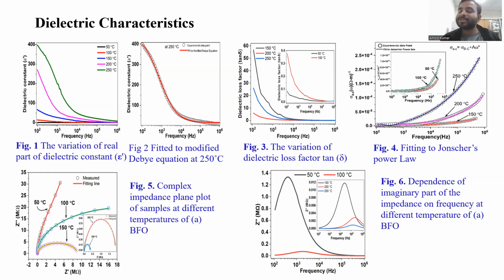In this fitting, we get S, and we draw the graph between S and temperature, and we know which type of model it is. If S decreases with temperature, then it is correlated barrier hopping. If it increases with temperature, it is small polaron conduction. In my case, it is correlated barrier hopping because it decreases with temperature.